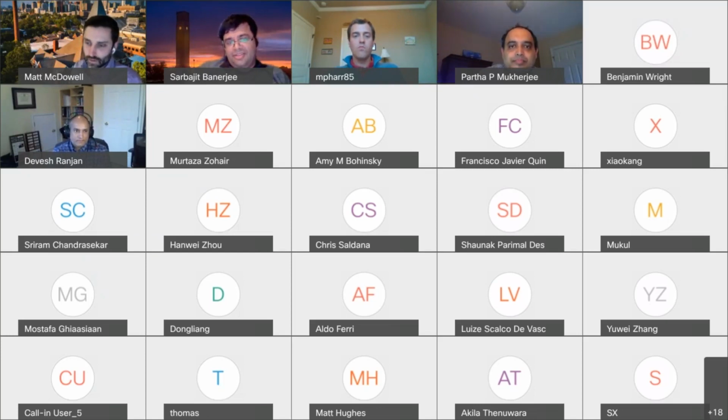Yeah, so we actually analyzed this. You probably didn't look at the details, but our interfaces were quite rough. There were asperities, and we analyzed in detail if there was a correlation between void formation and the quantified roughness of the interface, and we didn't find any. So we couldn't really tell from our experiments if there was a correlation. But I will say that this relates to the other Matt's presentation. It really comes down to mechanical deformation in many cases, because if you're stripping your lithium faster than it can be replenished by self-diffusion, then you have to mechanically deform the lithium to get it to fill that small void that wants to form. The mechanical properties the other Matt showed matter, and all these cells are under a stack pressure. So understanding how the structure of the interface, the extent of the stack pressure, and the mechanical properties determine deformation so as to prevent void formation is really important.